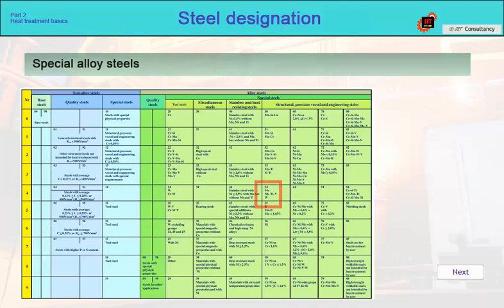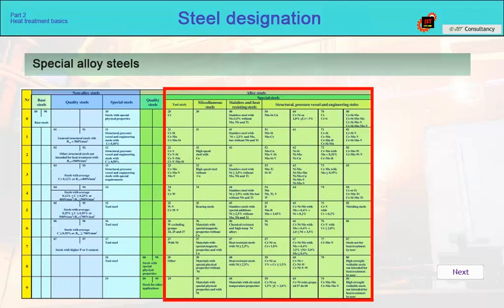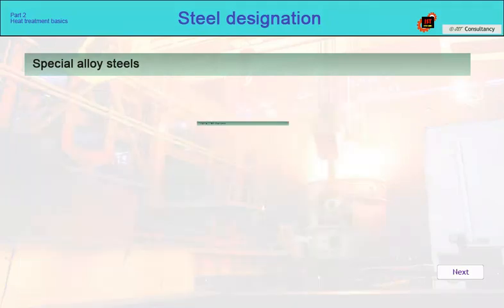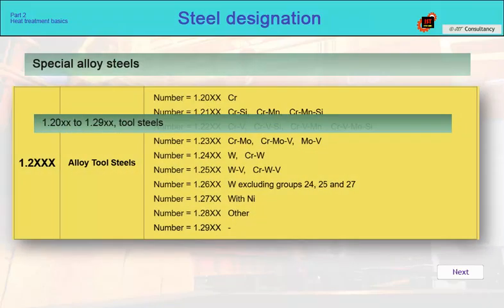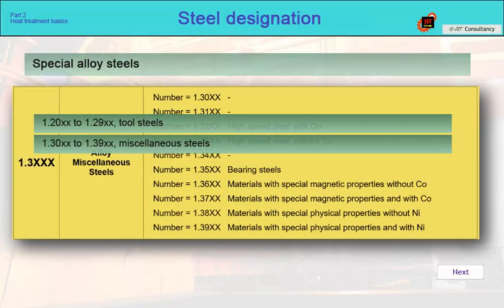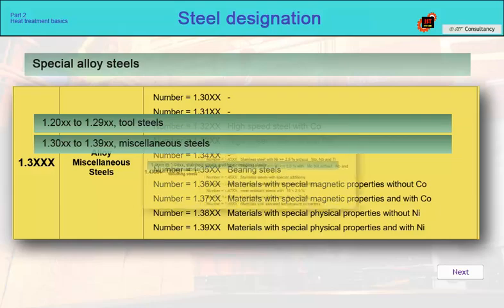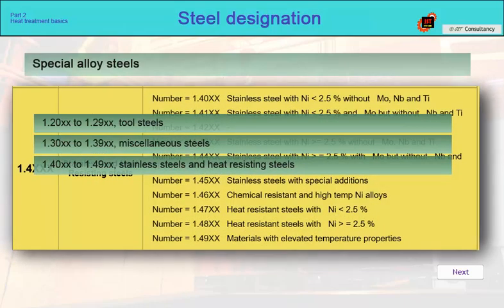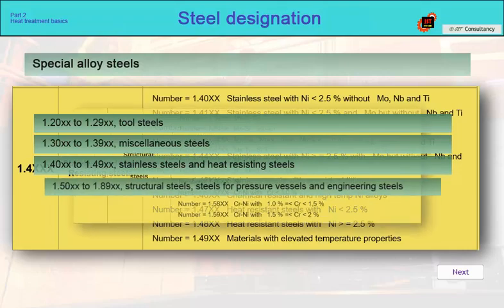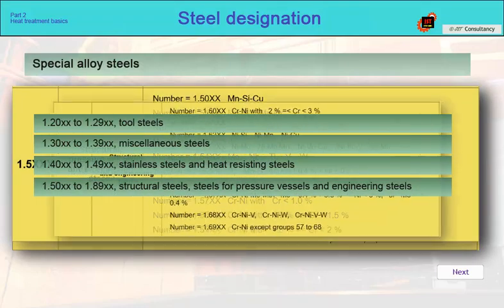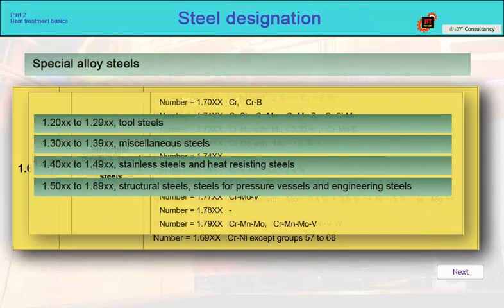In this table, the steels are classified according to the category and combination of alloying elements, or their percentage, into different groups, which are distinguished by a numerical code representing the first two digits after the dot. The basic groups of special steels are split into categories: 20 to 29, tool steels, 30 to 39, miscellaneous steels, 40 to 49, stainless steels and heat-resistant steels, 50 to 89, structural steels, steels for pressure vessels, and engineering steels.